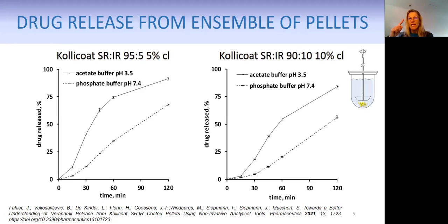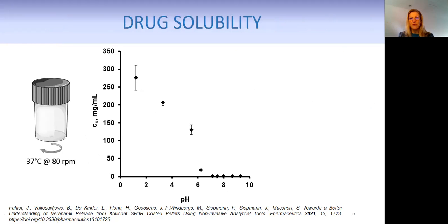Getting back to the fact that we have faster release in acetate buffer, this is actually attributable to the solubility of the drug within this medium, because verapamil hydrochloride is a weak base and shows pH-dependent solubility. So we checked the saturation concentration of verapamil in different media with different pHs by adding excess amounts of the drug in small flasks, filling them up with medium. And when we had an equilibrium between precipitated drug and dissolved drug, we sampled the supernatant and analyzed quantitatively the amount of drug dissolved.